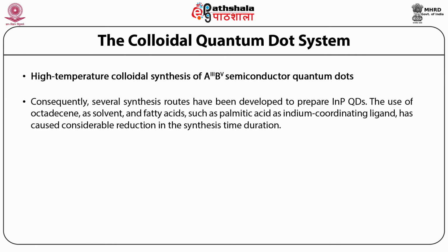Consequently, several synthesis routes have been developed to prepare indium phosphide quantum dots. The use of octadecene as solvent and fatty acids such as palmitic acid as indium coordinating ligand has caused considerable reduction in the synthesis time duration.